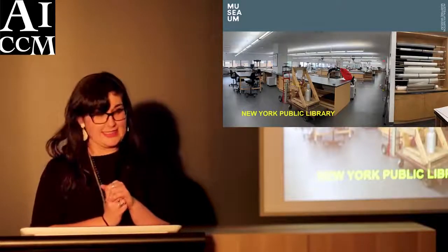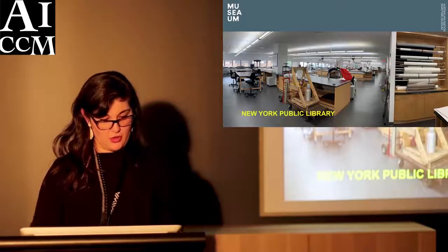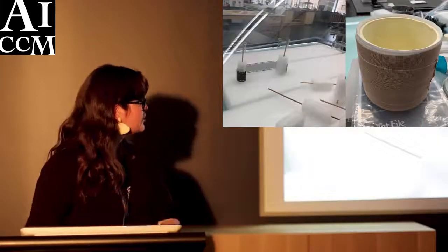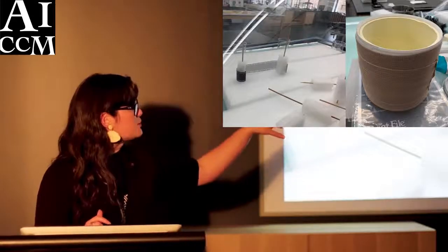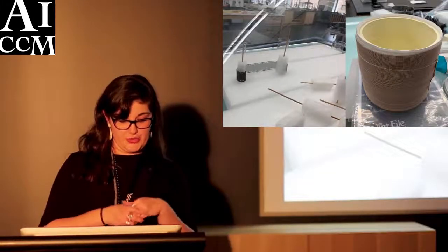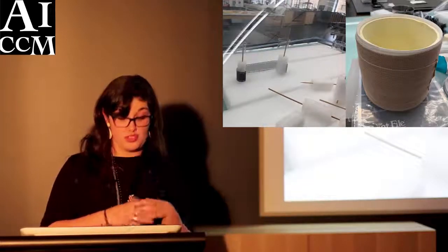Yeah, it's ridiculous. So she specialises in huge posters, 3 metres by 2 metres, but also huge collections or quantities of items. So I was with Jessica Keister, who's a photo conservator, and she took me through how they humidify rolls of acetate and nitrate. So it's a way for them to humidify it so they can be re-rolled on a big support with the emulsion side facing out, or they then, after they've humidified it, can cut them into smaller strips for storage. For nitrate, they used glycerin, water, and acetone to limit the amount of moisture, but for acetate they used just water, humidity in a chamber.